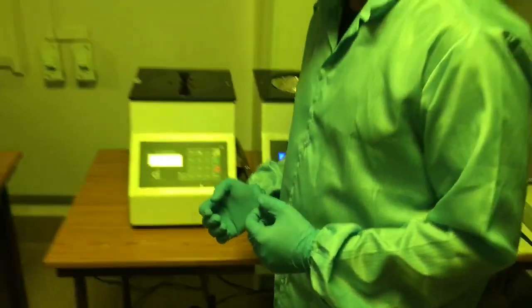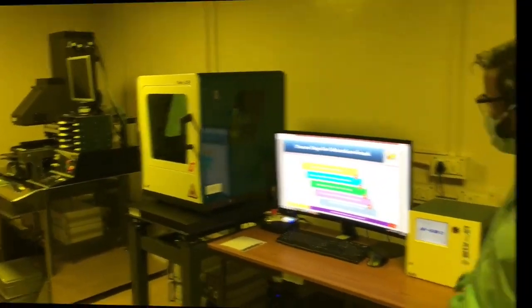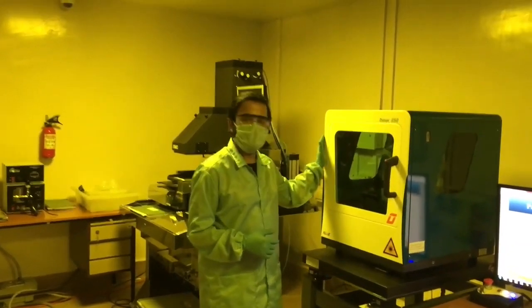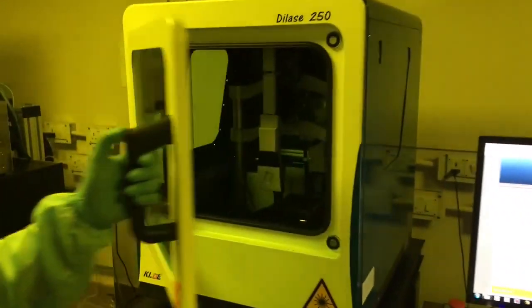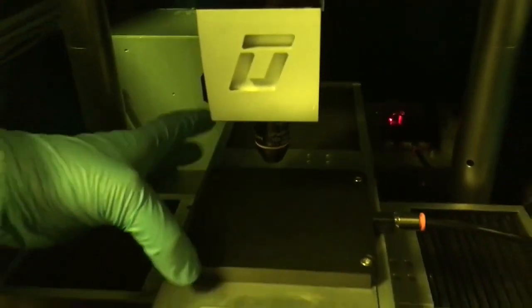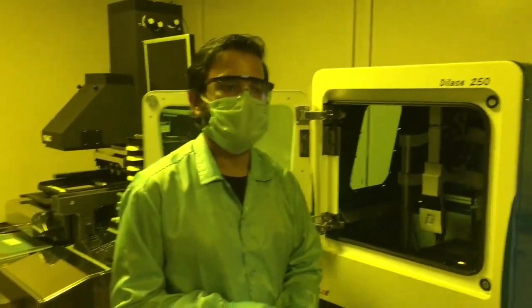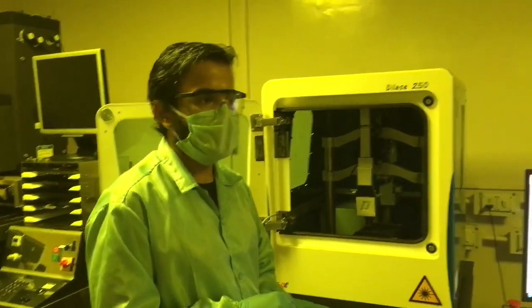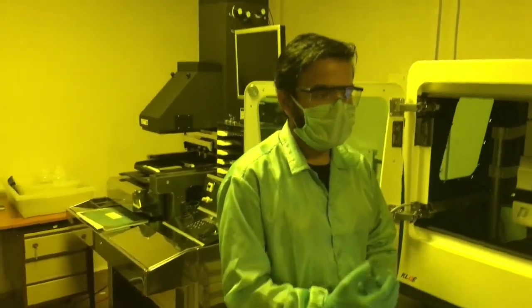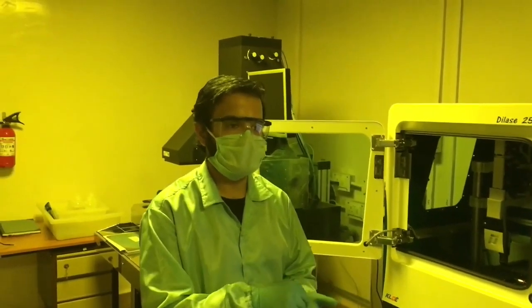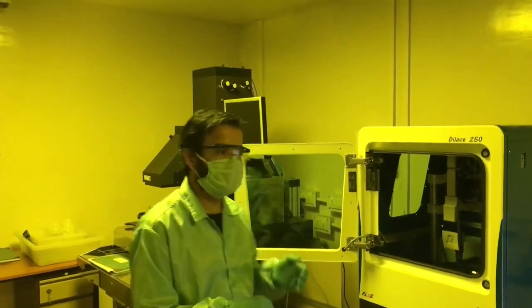Now we are going to use the lithography machines. There are 3 machines, 1, 2 and 3. We can do the lithography with this machine, which is called a mask writer. Inside this machine a laser source is there and then an optical system. The laser will fall from this head onto this chuck. Here we can keep our mask or even the spin coated wafers for direct writing. The laser spot size is about 2 micron and it will travel at 10, 20, sometimes 1 mm per second speed. The desired energy as well as the speed is selected as per the features which you want, and then the lithography can be performed. But this is a very slow process as the laser has to travel all the features one by one, and therefore a lot of time is consumed.